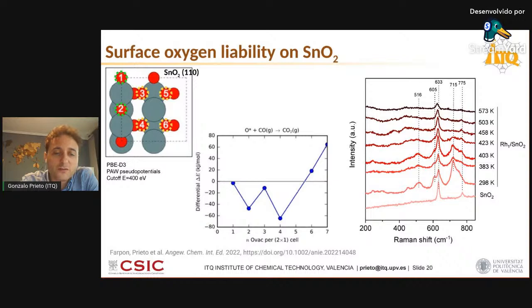So we first computed the thermodynamic stability of those surface oxygens in the reaction atmosphere pertaining to the hydroformylation chemistry, which is in the presence of syngas. Hydrogen is a reducing agent, but CO is much more reducing than hydrogen. So indeed, the reaction of the first two, the bridging type of oxygens, with CO to produce CO2 and then leave the oxide surface is downhill energetically, and it is subjected to essentially barrierless steps from the kinetic point of view. So both thermodynamics and kinetics tell us that losing those bridging oxygens on the surface of tin oxide is energetically and kinetically very easy under the hydroformylation reaction conditions, even under the mild reaction conditions we are applying for this process.